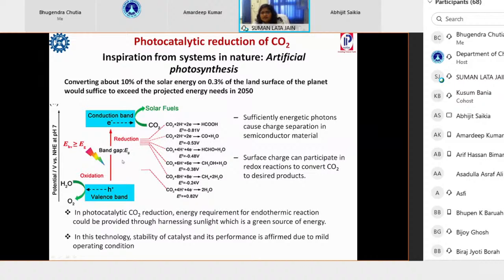There are a lot of semiconducting materials and heterojunctions, and in the literature plenty of materials are known for the photocatalytic reduction or conversion of CO2, but some drawbacks or limitations remain. As I said, under light absorption the charge separation takes place, but as the electron and hole separate, they immediately recombine. This is called electron and hole recombination. So one drawback is that the recombination of electrons and holes takes place very fast, so the availability of electrons for CO2 reduction is lower. Due to these reasons, the photocatalytic reduction or conversion of carbon dioxide to fuels under light irradiation is low, and the selectivity of product depends on this potential that we require.